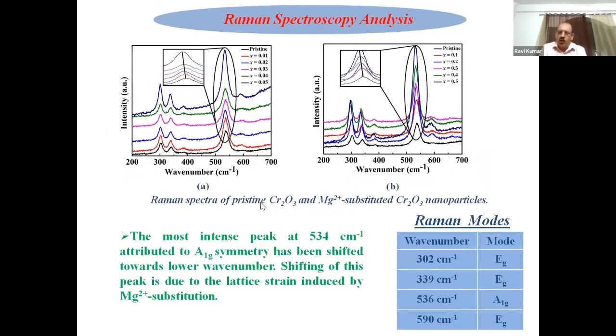And if you have to go with the molecular structure of that, you see the micro Raman experiment, Raman spectra of pristine and doped samples, and we have seen that the most intense peak, 534 centimeter inverse, attributed to A1g symmetry, has been shifted towards lower wavenumber. Shifting of this peak is due to the lattice strain induced by magnesium substitution, which we have seen through the X-ray also.